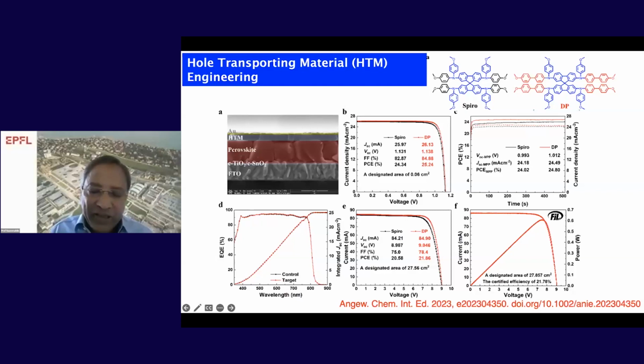So we increase the pi conjugation of the hole transporting material so that the positive charge created can migrate all over the HTM and therefore increase the stability. This was the basic logic of designing this new hole transporting material. Look at the efficiency data. So this is a spiro-based one, 24.34% efficiency.